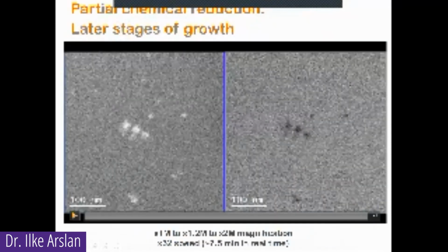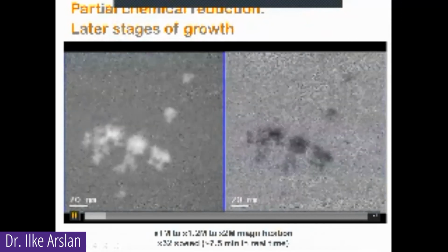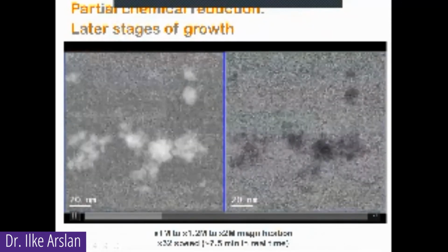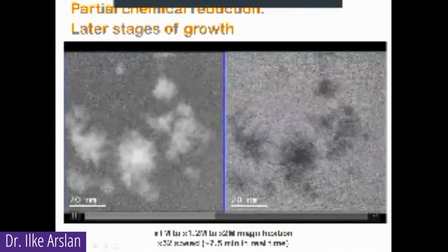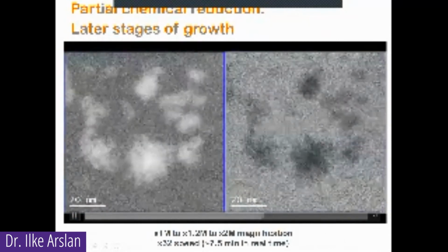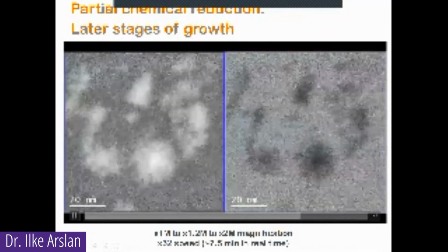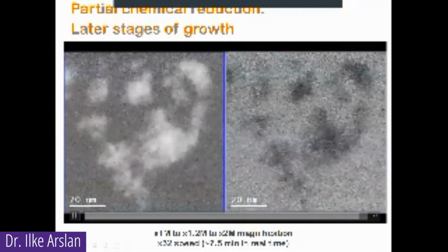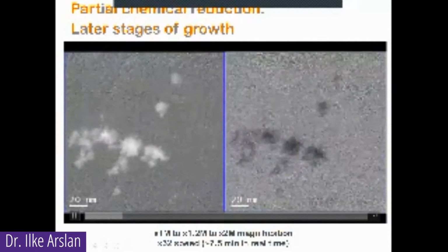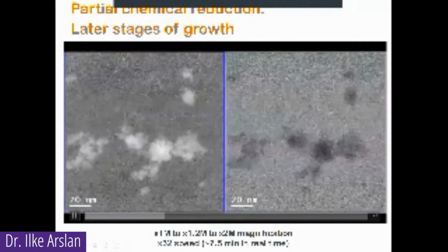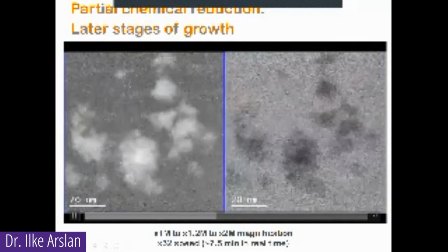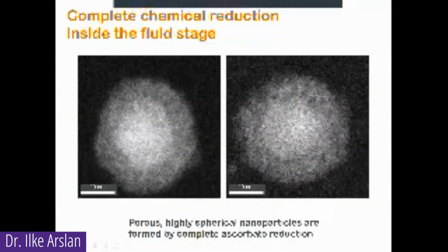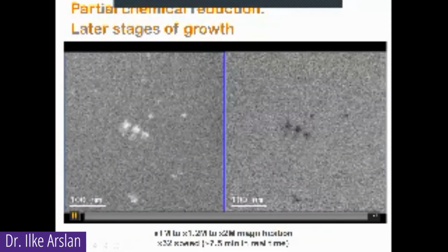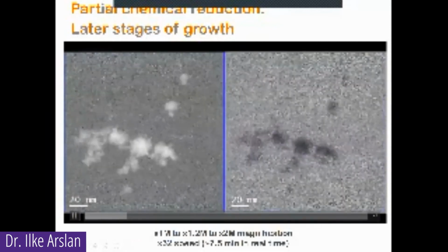Then at later stages of growth, we have these smaller particles come together. And you can see that they are kind of porous clusters. And these smaller porous clusters come together to form the nanoparticles. And this is why the nanoparticles are polycrystalline, because they have lots of different little clusters coming together to form one nanoparticle. So here are some of those porous nanoparticles that we formed in situ inside of the microscope at the end of this movie, basically, as a result of this growth.